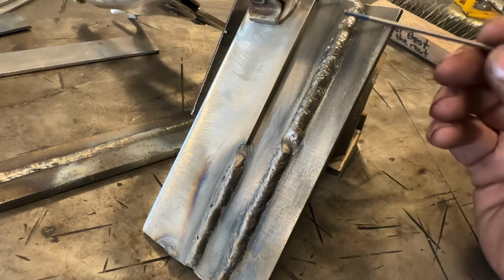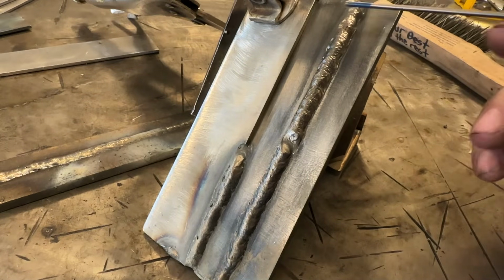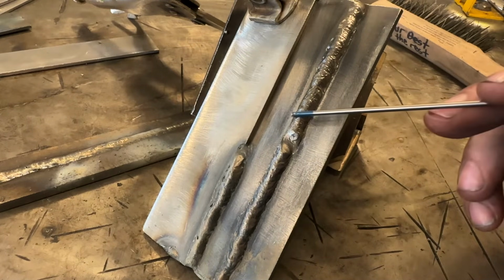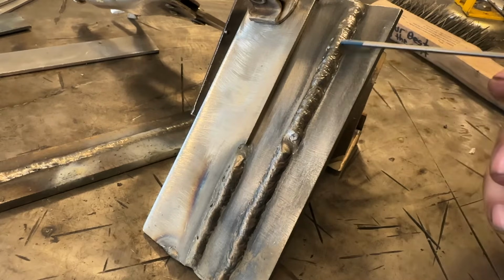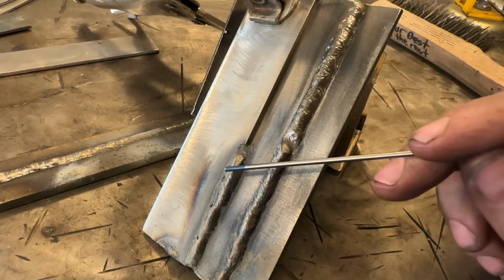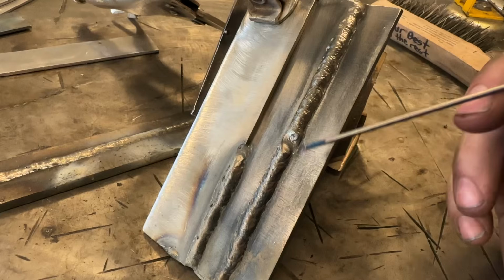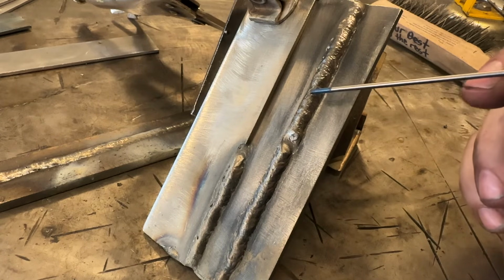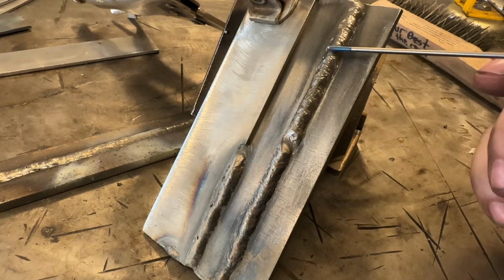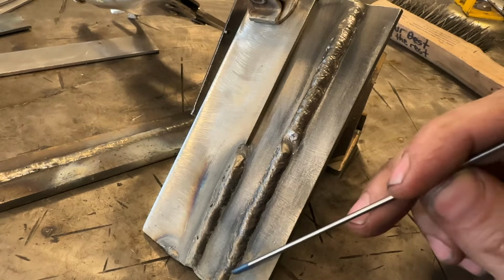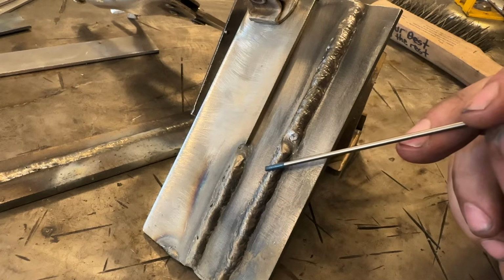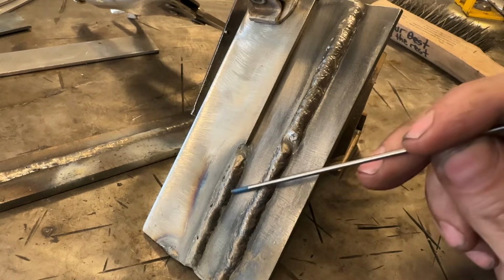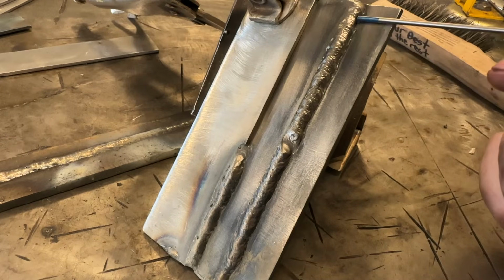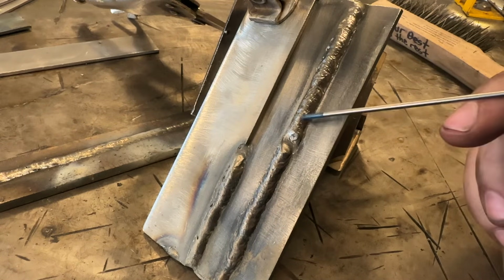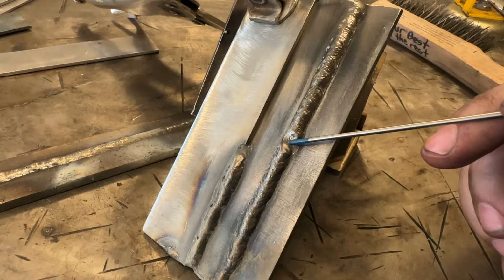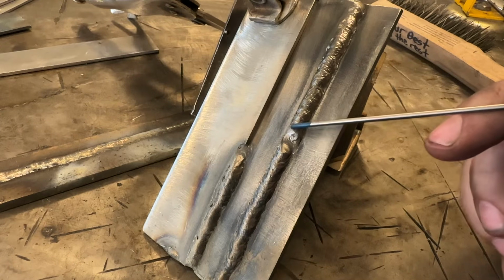So I flipped this plate upside down just to make it a little easier to see, but I welded this from the bottom up. Now when we compare this weld to these two, you can see just 0.3 volts created a weld that is flatter. I mean, without a doubt, look at the shadow line here. The shadow is telling you that this is slightly humped up. Same thing here. And here we have almost no shadow line, especially from about the halfway point up. Is looking real good, real consistent.